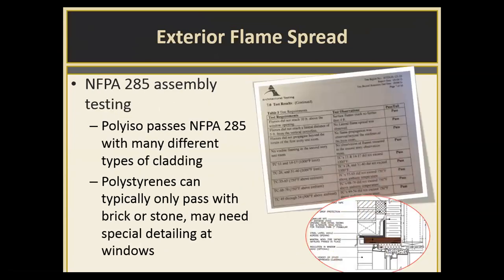And essentially, it's a 30-minute pass-fail burn. You can't trigger any of the thermocouples by reaching a temperature that's higher than what's limited. Flames can't reach certain points beyond the window header. And polyiso does very well in these tests, with all kinds of different claddings. Polystyrenes typically only pass with non-combustible claddings, brick, stone, stucco, things like that.